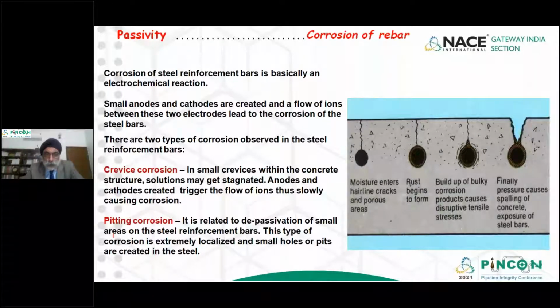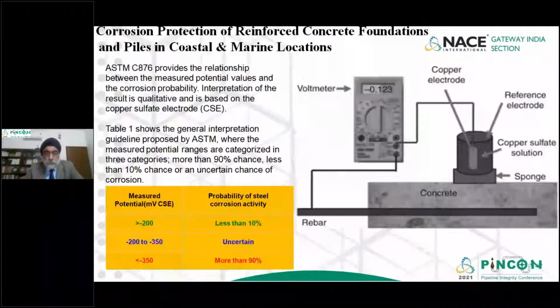Now, both these corrosions have very high corrosion rates. They are not dictated by normal corrosion rates. The corrosion rates can almost be 0.5 to 1 millimeter per year. And if the rebar is about 16 millimeter or 25 millimeter, in 10 to 15 years in a corrosive environment, the rebar diameters can reduce considerably, which would compromise the strength of the concrete, causing a catastrophic failure.